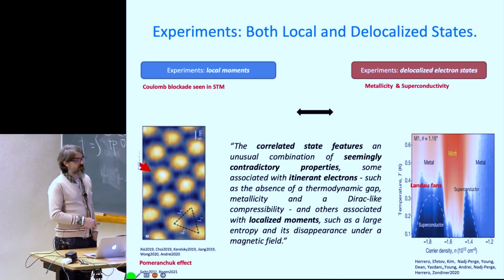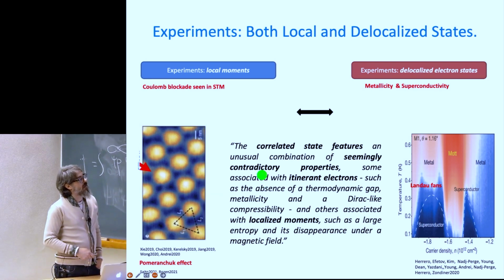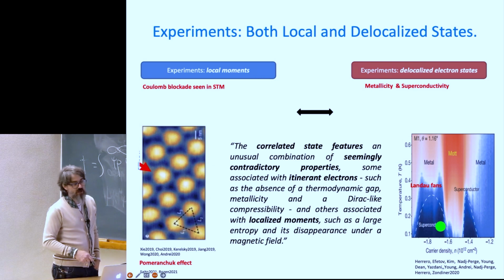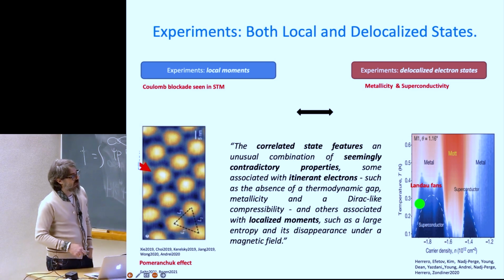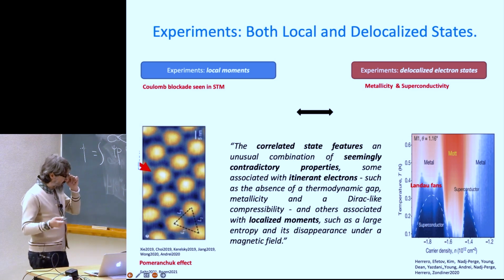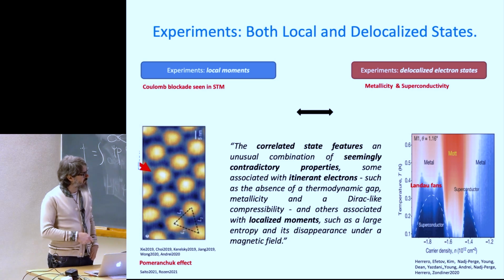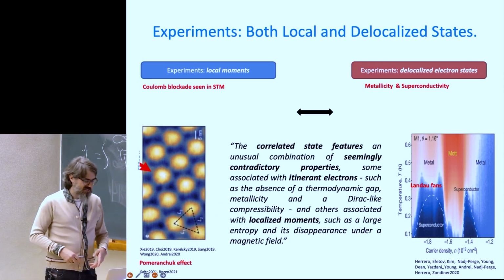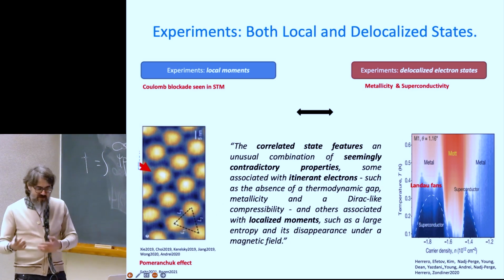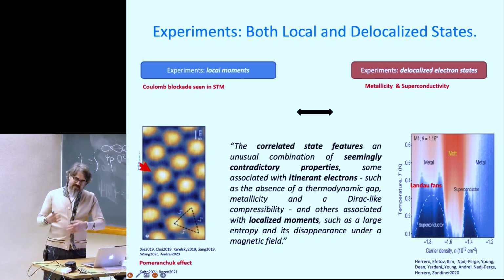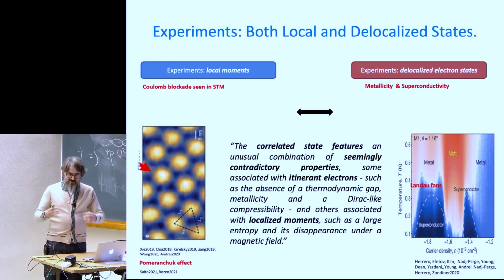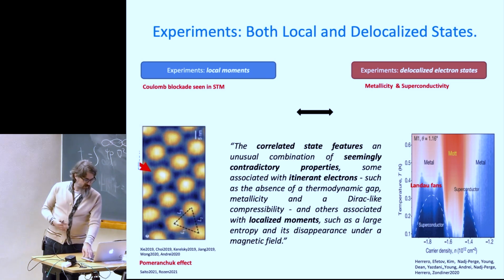If you were to see this, you'd say, oh, the system is very localized, right? It sits everywhere. But you know that there cannot be full localization because we see insulators, but we also see superconductors. And there are many other things that we see, such as Chern insulators, etc. A very famous paper in the field said the following: the correlated state features an unusual combination of contradictory properties, some associated with itinerant electrons and some associated with localized moments. The experimentalists like to present it as somewhere in between localized and topological. That somewhere in between doesn't really exist. The bands are actually topological, but they're topological in an interesting way.